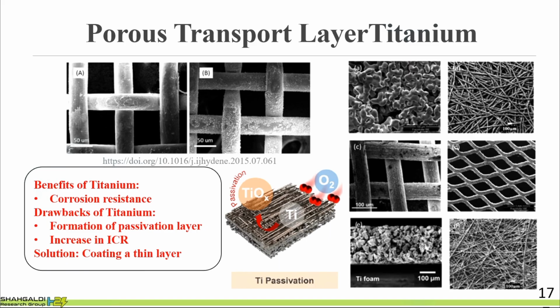Okay, so here I told you that we are using the carbon-based material in fuel cell, but we cannot use carbon-based material inside electrolyzer in the anode side. In the cathode side, we are fine. We can use the same GDL. But in the anode side, we need to use a porous transport layer that is a titanium-based material. So why? Because we have higher voltage, we have different conditions, and we have high voltage, and we have the more acidic environment.